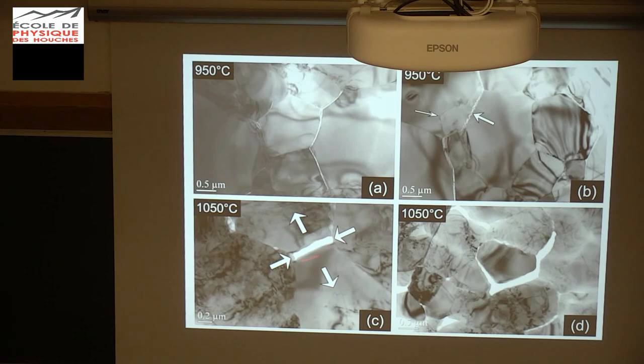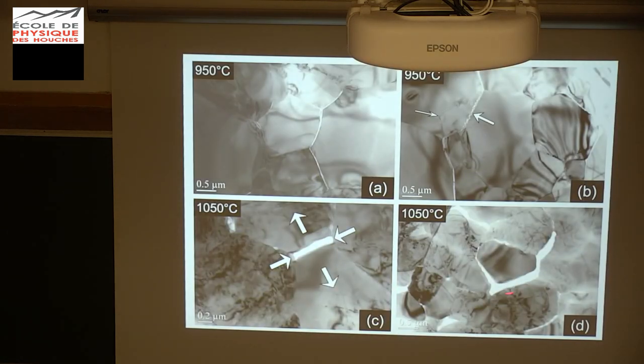At 1050 degrees Celsius we have this very nice almost geometrical opening, with some decreasing cells on the border. You can see it moved, but you cannot really pull it back together perfectly — you will have overlap of materials, which is also what the theory of grain boundary sliding predicts. But it can be quite drastic, with large opening. Some are still opening, and you also still have grain boundaries which remain tight. And remember, the confining pressure is 300 MPa, and the bulk steady state stress is well above the confining pressure.